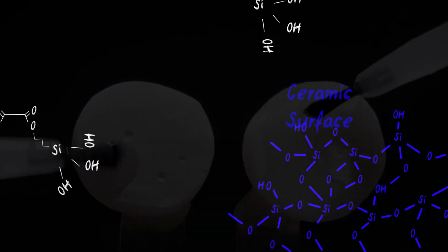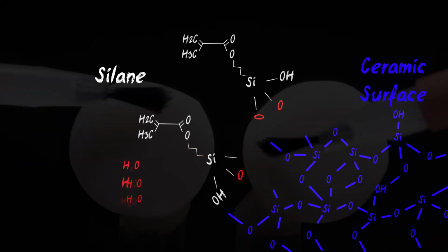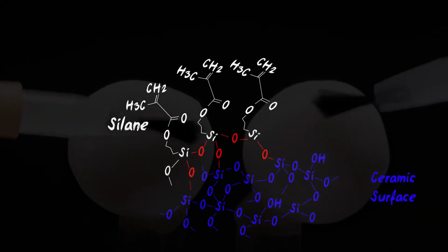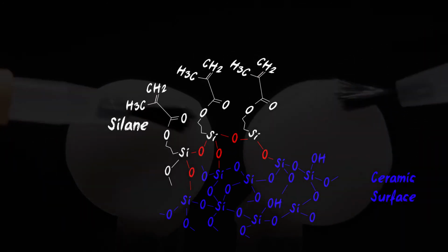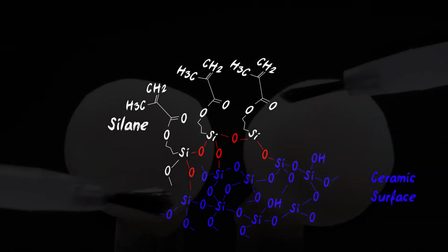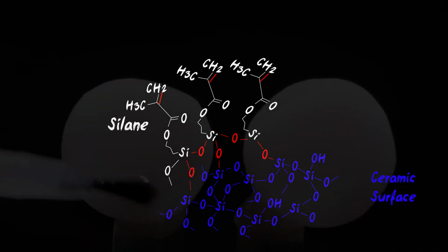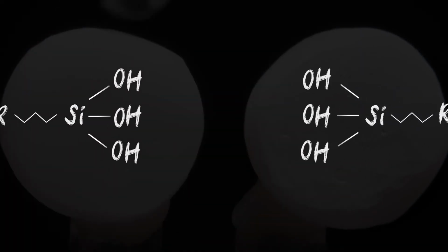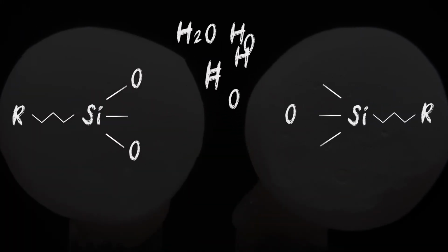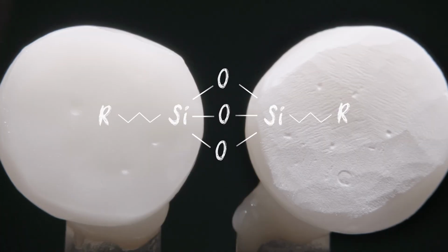When activated silane is applied to the surface, silane condensation occurs to form a siloxane linkage. Do not forget that on the other side, the silane has a layer of an organofunctional group. Adhesion to light-cured cements occurs due to the reaction between organofunctional silane groups and reactive free radicals formed during photoactivation of composite materials. One of the theories why a single component silane does not work is that over time the OH molecules of the pre-activated silane interact with themselves and precipitate.